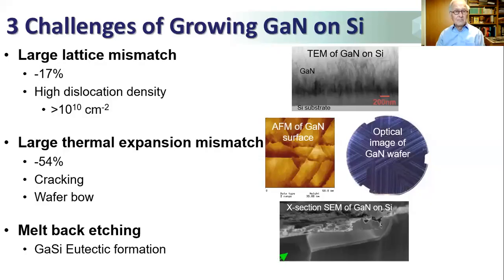So these were the challenges of growing gallium nitride on silicon. As I said, the standard gallium nitride LEDs you could buy then, which were very expensive, were grown on sapphire or silicon carbide. The first challenge is this very high lattice mismatch of 17%, which gives you a very high dislocation density.